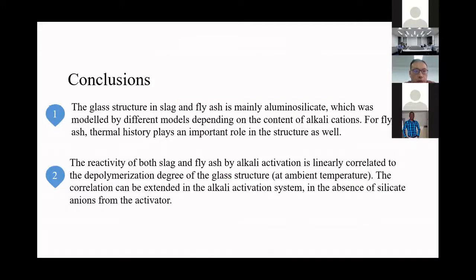In the end, we come to my conclusion. The glass structure in slag and fly ash is mainly aluminosilicate, which was modeled by different models, depending on the content of alkali cations. For fly ash, thermal history plays an important role in the structure as well. Despite that, the reactivity of both slag and fly ash by alkali activation can be linearly correlated to the depolymerization degree of the glass structure, even for fly ash, at ambient temperature. If the temperature is raised, this correlation may not apply.